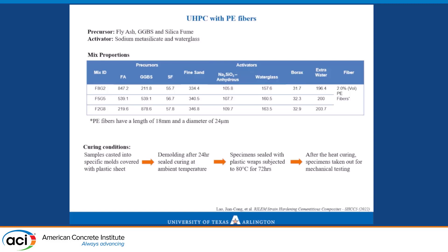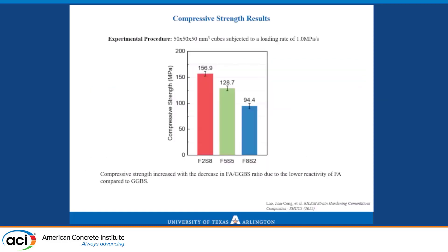The activators used were water glass and anhydrous sodium silicate. We also wanted to partly replace the anhydrous sodium silicate with nano silica, but that work is not completed so I am not presenting it. There was also a retarder from borax, and the water-to-binder ratio was close to 0.3. Here are the compressive strength results with synthetic fibers at 2%, varying the fly ash content. Just as with steel fibers, higher the slag content, the higher the compressive strength. However, the compressive strength — around 160 MPa — is lower than what we had with steel fibers.